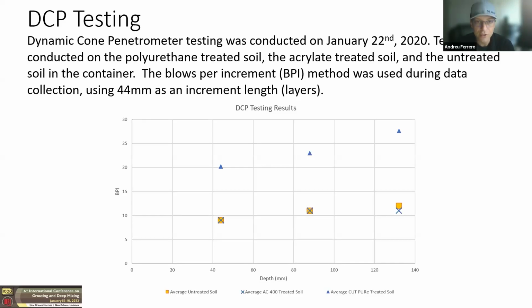Now, the polyurethane treated soil doubled the penetration resistance over the untreated soil. And the acrylate treated soil didn't have really any change in penetration resistance from the untreated soil. Now, the acrylate material reacts and forms a gel, so we don't really expect that to increase the penetration resistance, but it will add cohesion to the soil, which will increase the stand-up capacity of that soil.